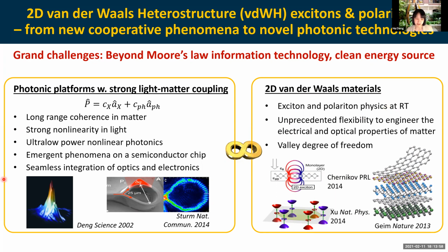With conventional materials, we do all of this at liquid helium temperature. But in those van der Waals materials, excitons survive at room temperature. You never hear about excitons when you use your electronic devices or LEDs, because the excitons dissociate. They don't have enough binding energy to survive at higher temperatures. But in these materials, they will be the dominant excitation and will dominate the physics if we ever use them to make devices.